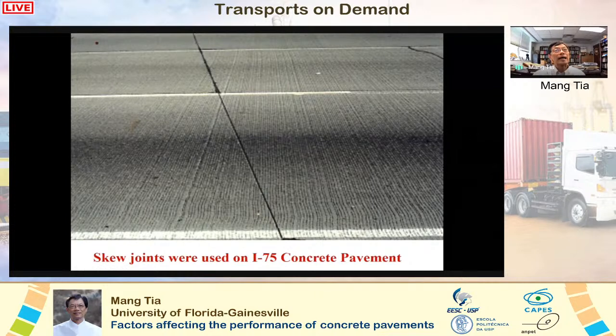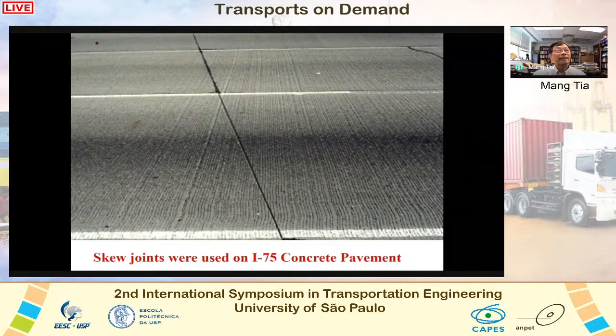The rationale behind the use of skew joint was that when trucks' wheels pass over the joints, only one wheel would pass over the joint at one time, and thus the impact effect would be lessened. And the rationale behind the use of variable joint spacing was that this would lessen the resonance effect. If the slabs are of different lengths, if they were to vibrate, they would vibrate at different frequencies, and thus the chance of all the slabs vibrating at the same resonance frequency would not happen.